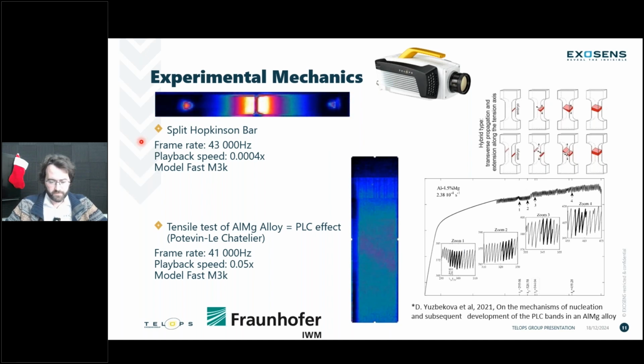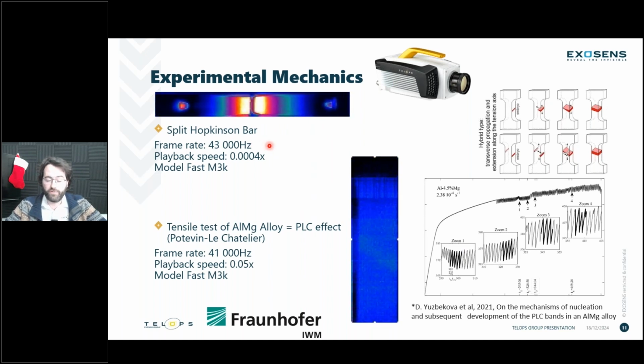So let's move on to the infrared cameras directly, so not hyperspectral anymore. We've been doing some great experimental mechanics measurements. At the top here, this is a typical split Hopkinson bar. That kind of measurement is pretty standard in the industry. They're really the ones pushing the frame rate as much as possible with our cameras. This was done in Germany when I was visiting for some demos and conferences. We had a group at the Freiburg University doing some split Hopkinson bars in an amazingly long underground tunnel. And we're able to push that frame rate to 43,000 hertz to have a really clear measurement for multiple frames at the point of separation of that split Hopkinson bar.